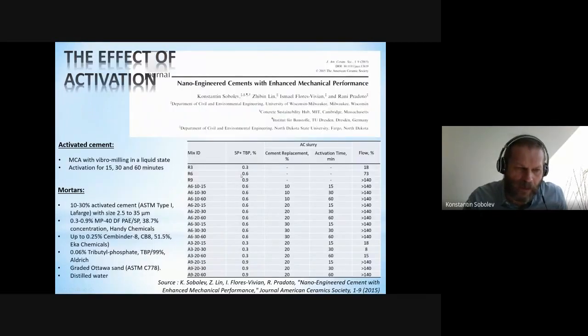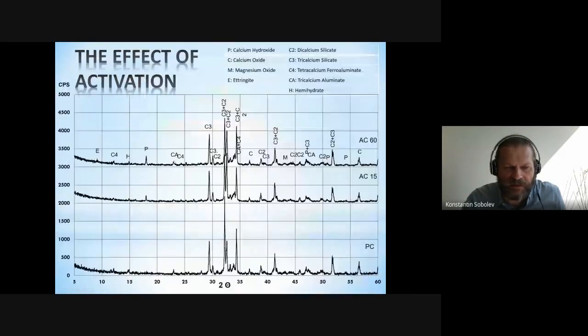To prove this, we ran an experiment to produce a CSH nanoseed or hydrated cement products using an experimental program. And if someone is interested, you can have a look at this paper published back in 2015. We used different activation times and different cement replacement with activated cement slurries. You can see that most of the compositions were extremely fluid, and we used also superplasticizer to produce the activated material.